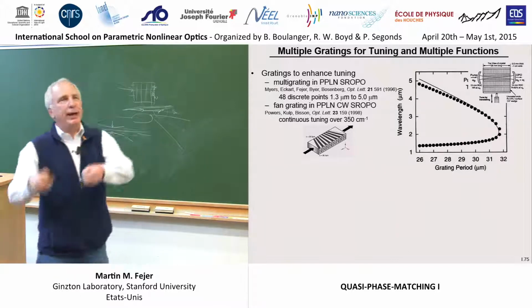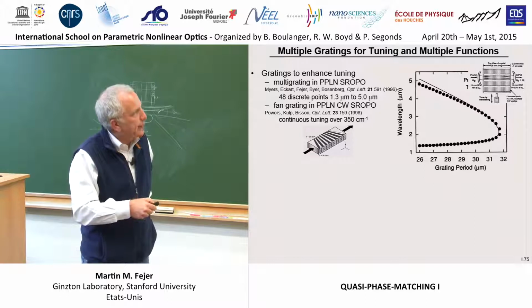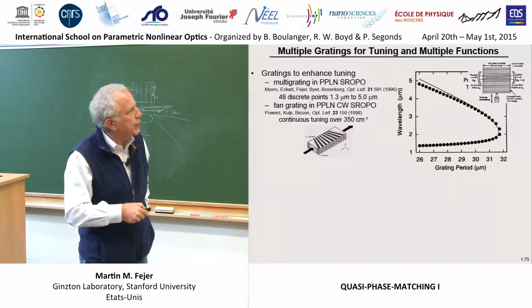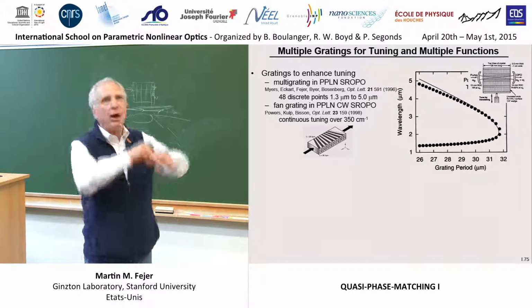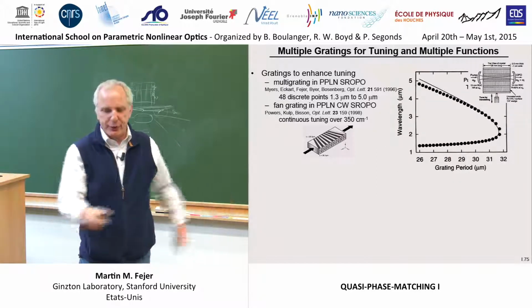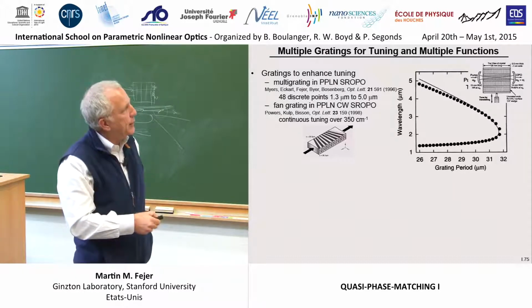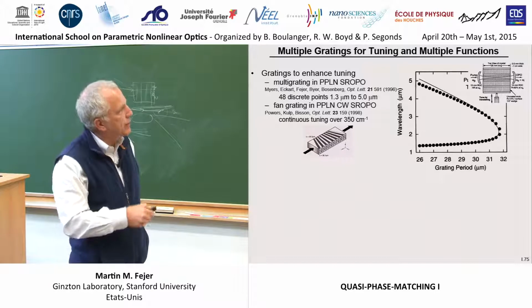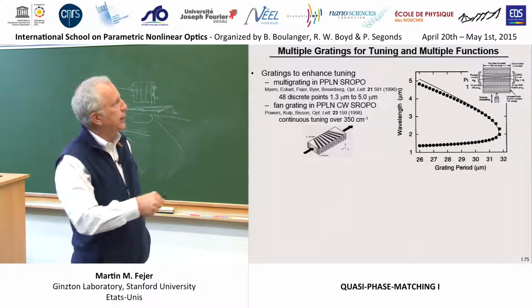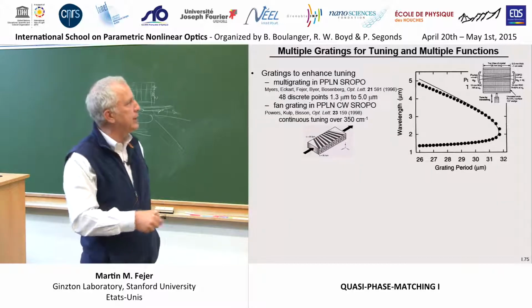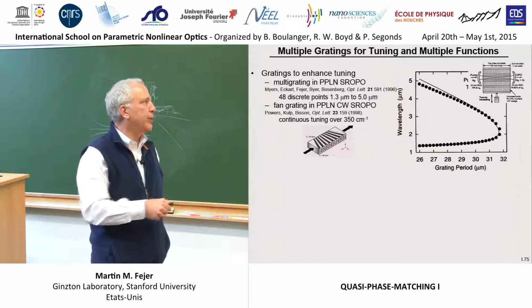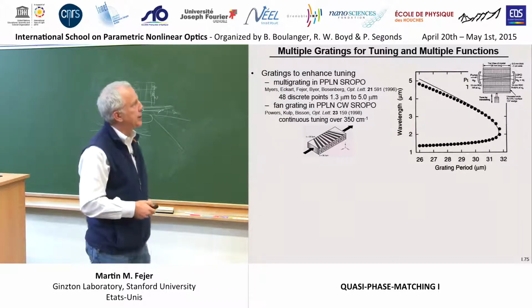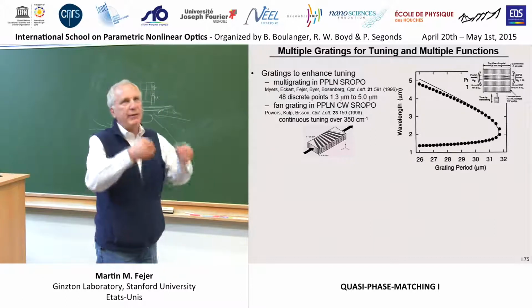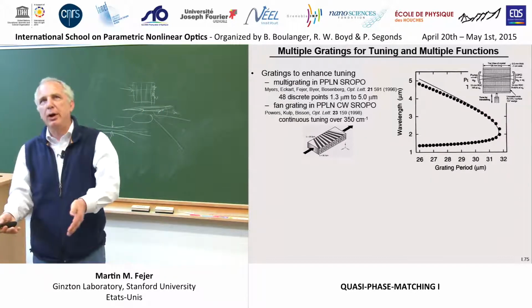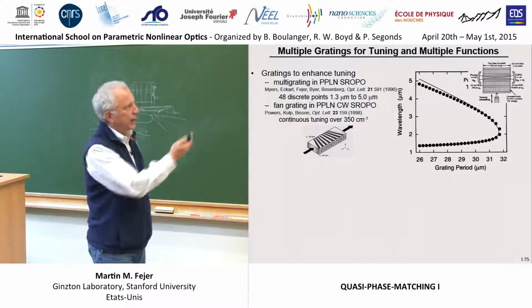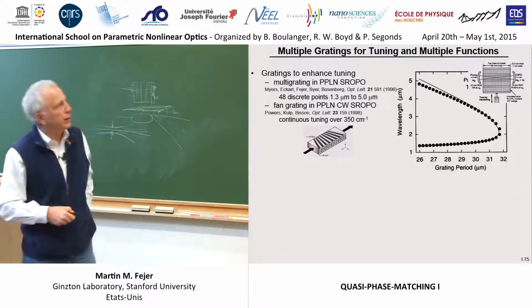Okay, how you can use multiple gratings. For example, this thing I showed where you had 26, 26.2 and 26.4 micron period gratings, all fabricated just choosing a mask that had those different patterns on it, and then translating that through a cavity, and you can get a set of discrete pairs of signal and idlers spanning the whole transparency range out to 5 microns, and with a 1 micron pump pushing to 1.3 micron wavelength for the signal. Sometimes having discrete tuning points is advantageous because you know where you are. You just have to calibrate to within one grating period and you know what you're working with.